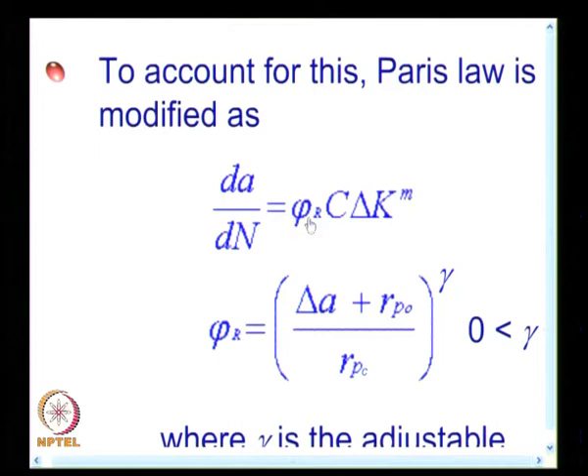You have dA by dN is given as phi of r multiplied by C delta K power m. Normal Paris law would not have phi r, and phi r is defined as delta a plus r p c, it is a typographical error, divided by r p naught. You please change this, this is whole power gamma. So, what you will have is an overload plastic zone length at the denominator, and delta a plus whatever that you get for the cyclic, that is r p c, you put it as r p c, do not write it as r p naught, it is a typographical error here. So, you will have a factor less than 1, which indicates that the growth rate is retarded. And we will also see what is the geometric representation of these quantities.